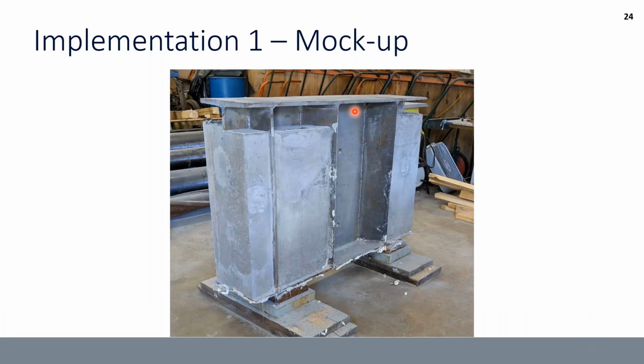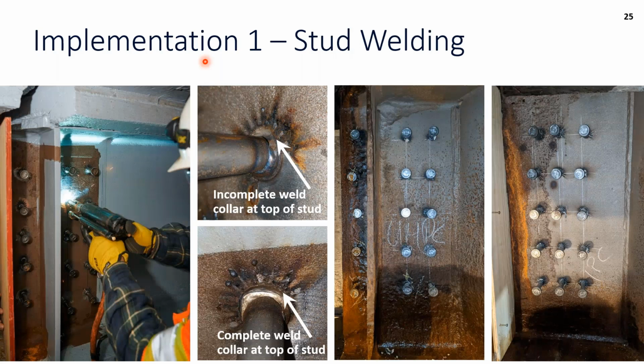And here is a view of the final mock-up. And you can see this is a little bit of a difference from the mock-up. This is the height of the UHPC that was stated in design. There was a gap there. However, when we actually moved to the field, some of the later pictures, you'll see we did end up casting all the way to the bottom of the top flange. So now moving into the field, working on the stud welding.